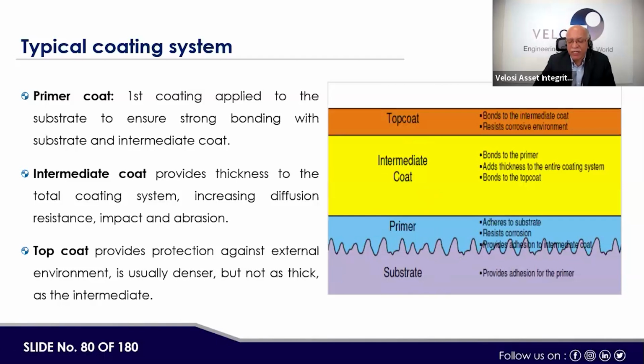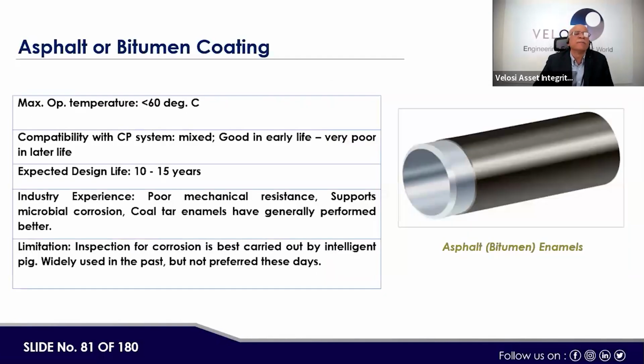There are various types of coating systems, for example, asphalt or bitumen coating, which operates up to 60 degrees Celsius, and its life is 10 to 15 years. Compatibility with the CP system: good in early life, very poor in later life. This is the case. These limitations are there. Inspection for corrosion is best carried out by intelligent pigging. I'm not in favor of intelligent pigging personally.